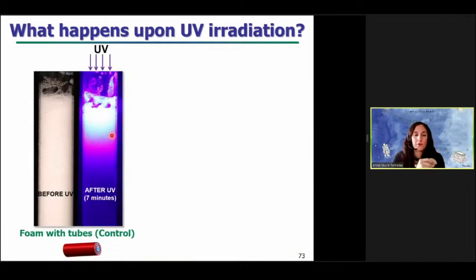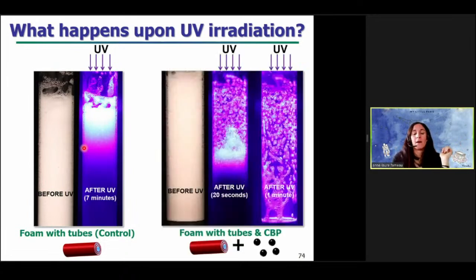So then we produced some foams, and we had a look at what is happening under UV irradiation. So here you can see the control foam just with the tubes. This is the picture before UV, and then the picture after UV radiation from the top of the foam after 7 minutes. And as you can see here, nothing happened. The foam is still stable upon UV radiation. But when we do exactly the same experiment with the foam based on tubes mixed with carbon black particles, you can see that just after 20 seconds of UV radiation from the top, you observe very fast foam destabilization. And after 1 minute of UV radiation, you don't see the foam anymore. So the presence of these carbon black particles really destabilizes the foam upon UV radiation.